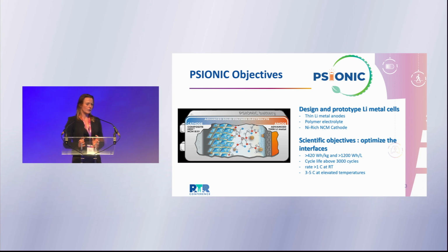We will also use lithium metal anode, which will be very thin. And we will also use nickel-rich NMC on the cathode side. And in between, we are trying to develop a polymer which will integrate both the catholyte and the electrolyte. The aim at the end will be to reach very high energy densities, higher than 420 watt-hour per kilogram, and more than 1,200 watt-hour per liter.